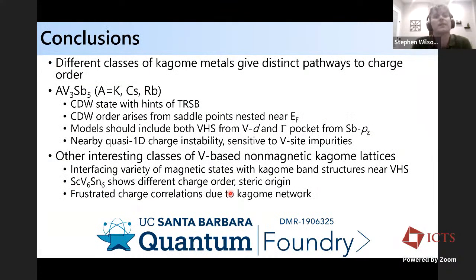I'll just conclude here by saying that, hopefully, I gave you an overview. There are different classes of Kagome metals with distinct pathways to charge order. One is a chain instability that I just talked about, and the other is this in-plane 3Q distortion with some interlayer correlations. The 135 system I already talked about, but then the second class, the scandium system, shows a different, interesting pattern of charge order with frustrated charge correlations, but that frustration is also due to the Kagome network.